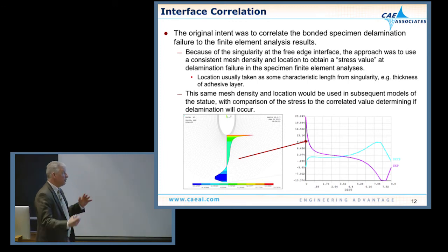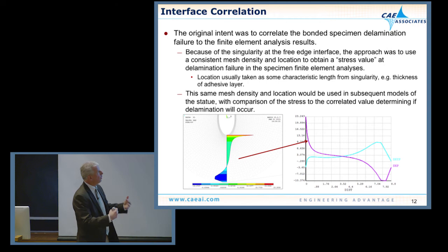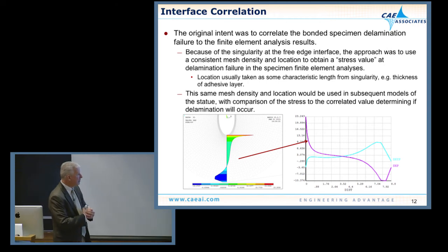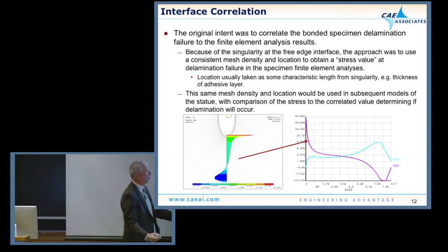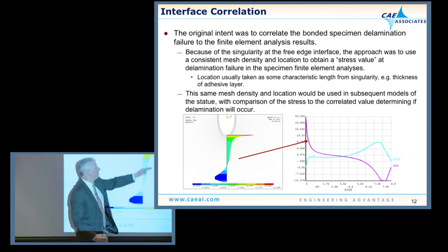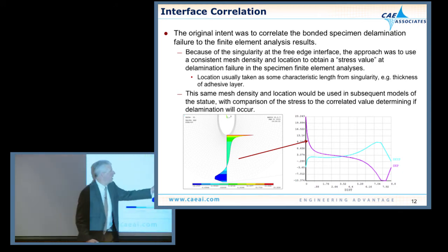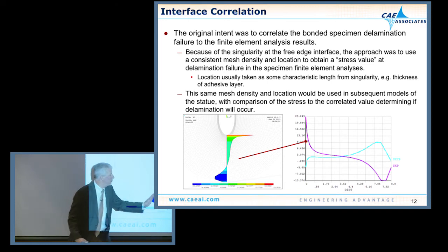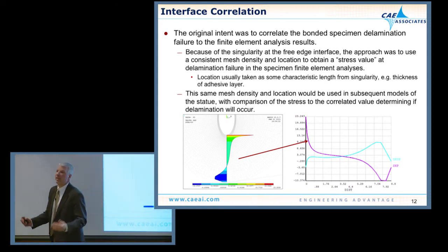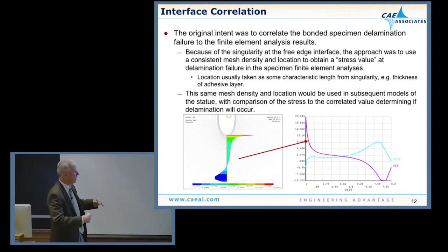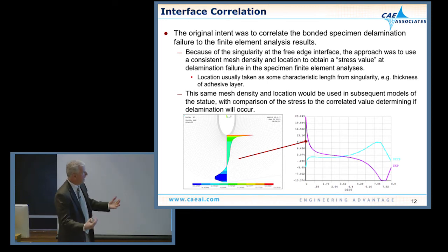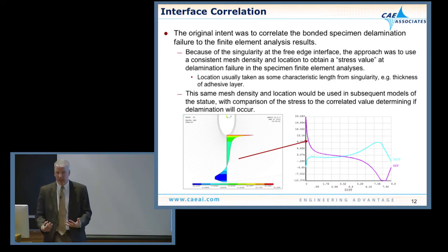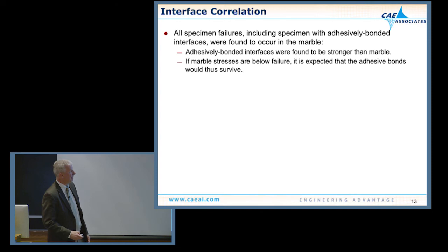Okay, so then we went to the delamination specimens and we started looking into that. And again, at this point, we were at the singularity, at the point where we have the adhesive. If you look at the stress when it comes to a free edge, that stress is starting to head to infinity. So what we can do is run that and find out what the load level is, and we can come up with a representative stress using a particular mesh density to come up with a failure criterion. So that was our approach.